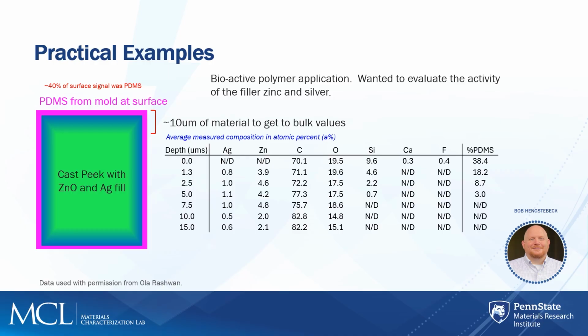And they're looking in this case at saying, we're going to take the material we have, which is a PEEK, and they're going to have zinc oxide and silver filler. And they want to be able to know, does this mold process allow them to have a bioactive surface? As it turns out, the PDMS from the mold gets onto the surface, and so on the initial surface we're primarily seeing a PDMS contamination, so it's polydimethylsiloxane. On top of that, we're not seeing a lot of the silver or the zinc at that surface. And so if we want to remove that initial contamination, we then want to know within depth, are they getting this bioactive area at the surface, or is there something else going on?